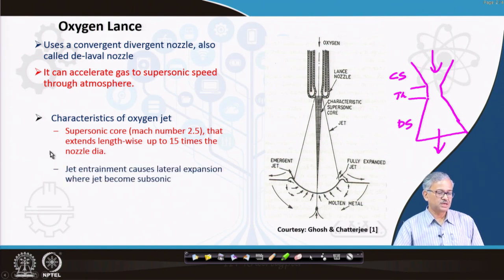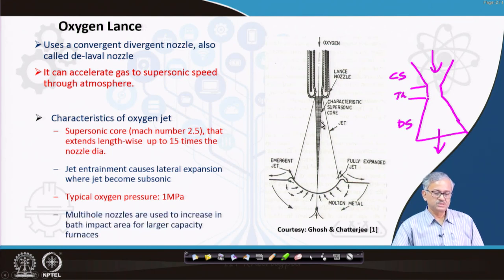Second characteristic is the jet entrainment, which causes lateral expansion, where the jet becomes subsonic because of the air entrainment, okay? And there is a lateral expansion of the oxygen jet, because it has taken a lot of air into it. And it becomes subsonic. This white portion is the subsonic portion. For the typical oxygen pressure used in the upstream region, approximately 1 megapascal of oxygen pressure is used, okay, to produce this supersonic jet.